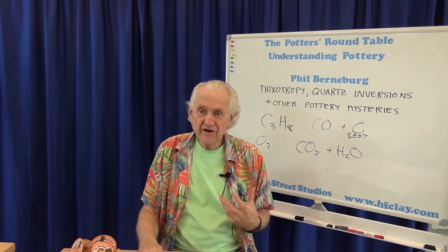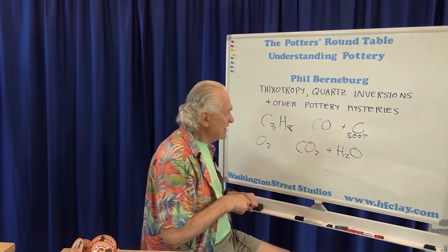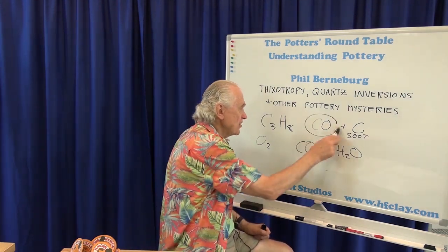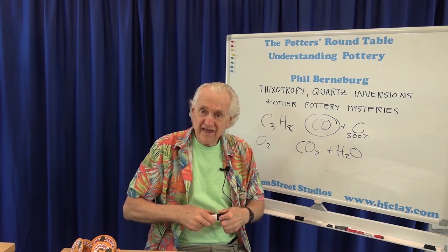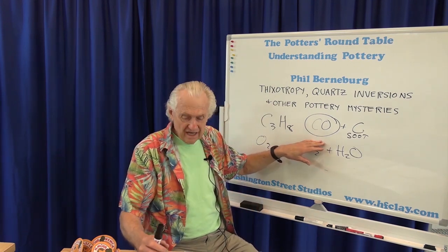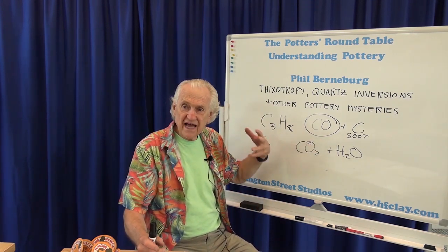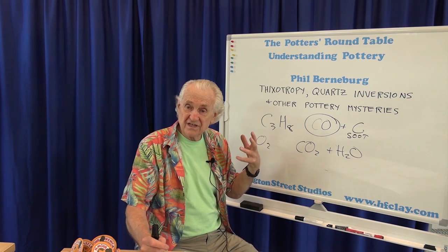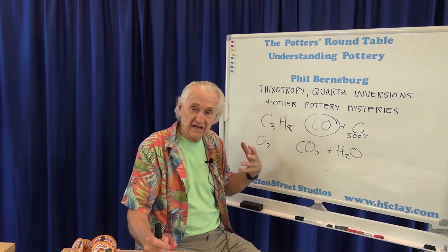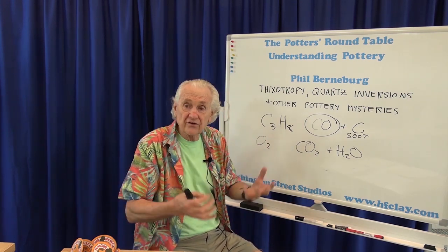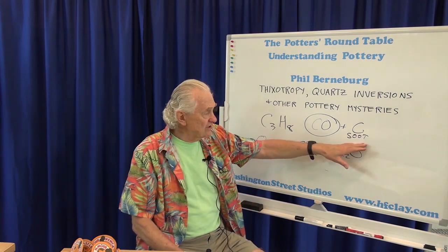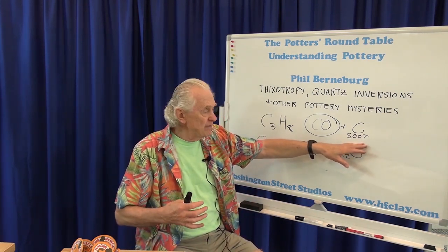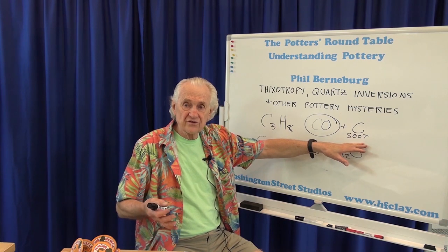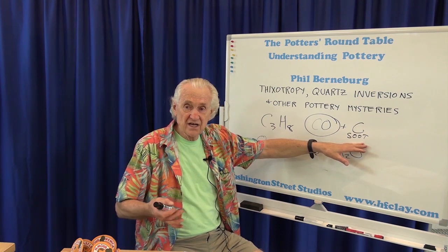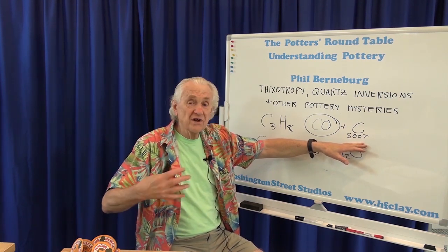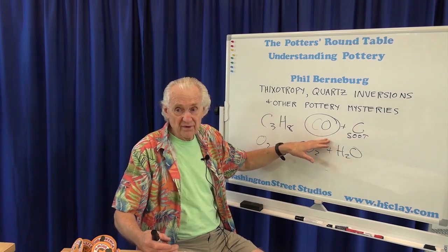So when you're firing reduction, what we actually want to make is carbon monoxide. This is chemically active, and this is what is going to react with the colorants, especially things like iron and copper in the clay and in the glazes, and bring about the color changes that we want. If we over reduce, we make soot. Soot doesn't do anything as far as reduction. It's just a product, but it means we've made too much reduction. We want to make carbon monoxide.